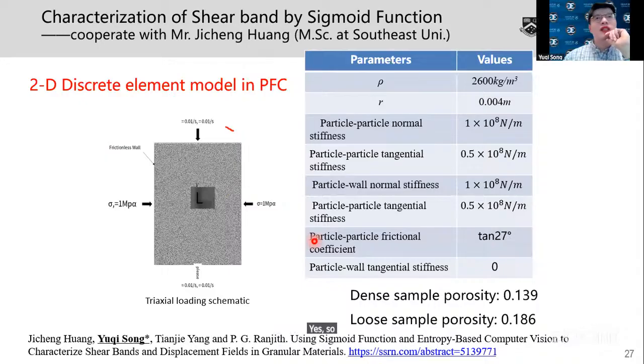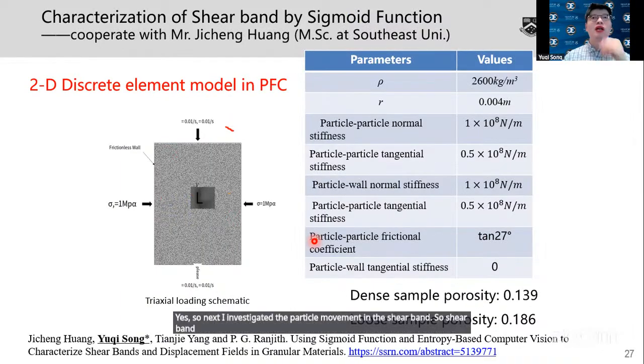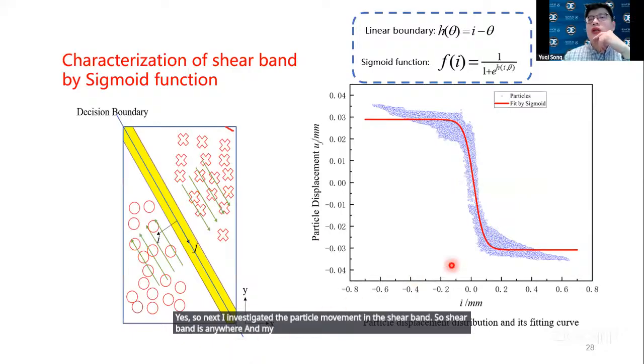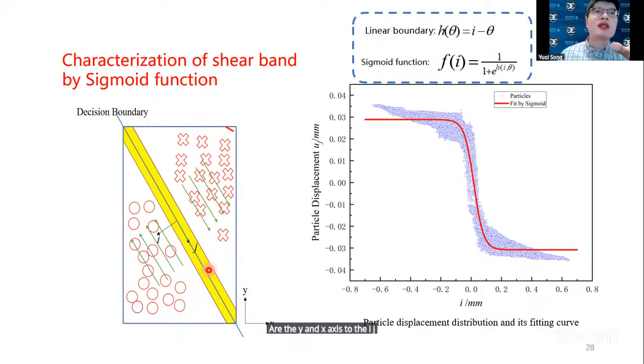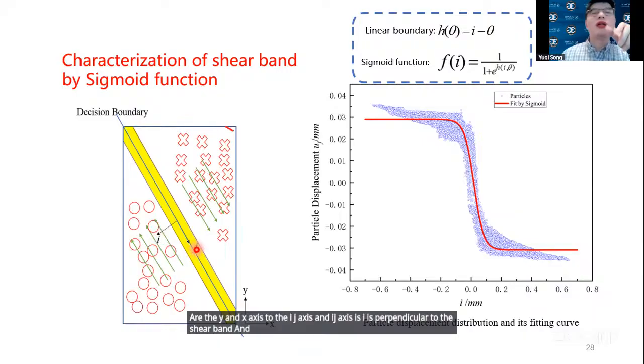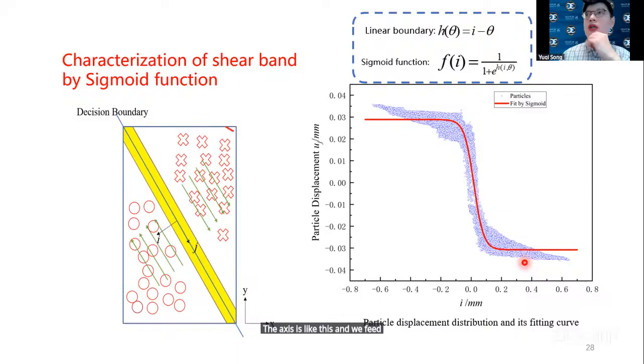Next I investigated the particle movement in the shear band. The shear band is everywhere, and my method uses a function called the sigmoid function to characterize the particle movement in a shear band. We first turn the common x and y axes into ij axes, where i is perpendicular to the shear band and j is along the shear band, and we can see that things become easier. We can see the particle displacement using the ij axes is like this, and we fit it with a function called the sigmoid function.